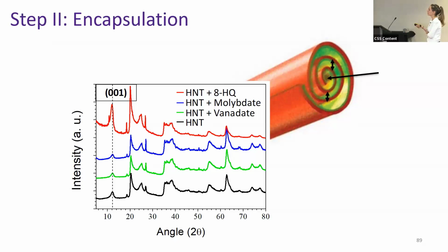So if the corrosion inhibitors were intercalated within these 2 layers, this interplanar distance would increase, and according to Bragg's equation, we would observe a shift towards lower 2 theta values in the spectra. We didn't observe such a shift in the case of the inorganic corrosion inhibitors, but in the case of the organic one, we observed a very, very slight shift. So this suggests that the inorganic corrosion inhibitors are loaded in the inner lumen, while the organic, we've got a mixture of molecules in the inside of the nanotube and intercalated within the walls.